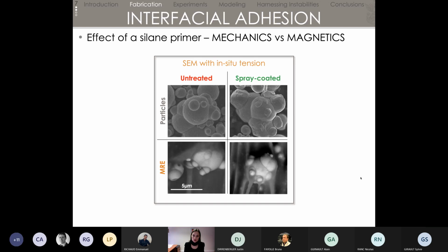Then if we take two samples, one treated and one untreated, cut them and pull on them inside a scanning electron microscope, we can see indeed the effect of the silane primer. On the left side, you see that the matrix detaches very cleanly from the particles. And on the right side, you can see that thanks to this silane primer treatment, the matrix remains attached much better to the particles as you pull on your sample. These pictures are nice, but it's still at the very microscopic scale. So what we're going to do later is look at the macroscopic behavior of our sample.